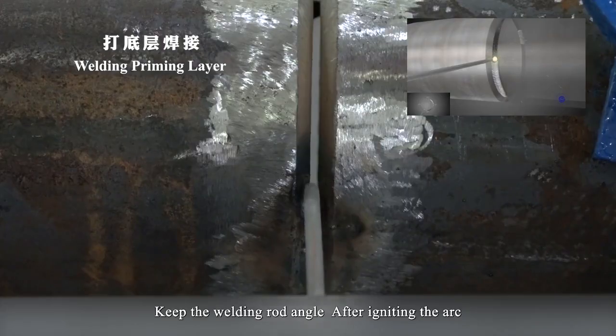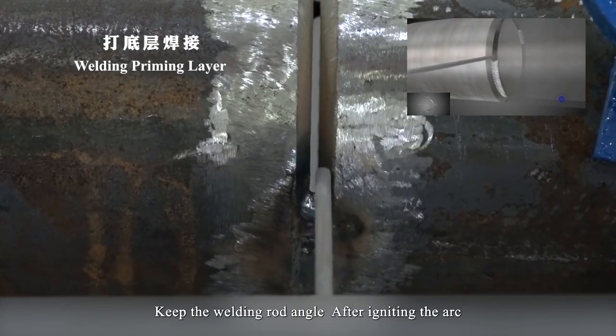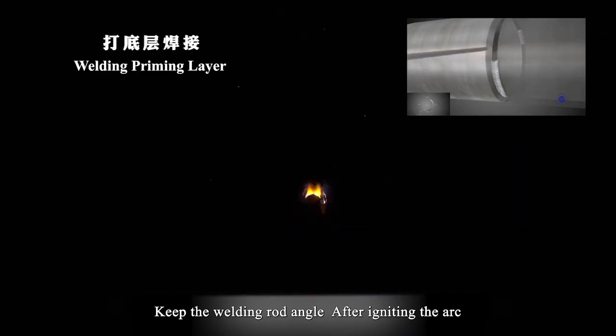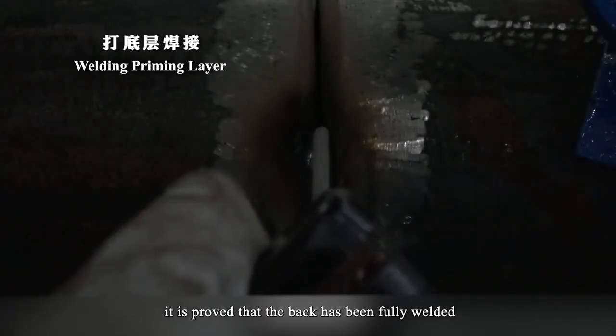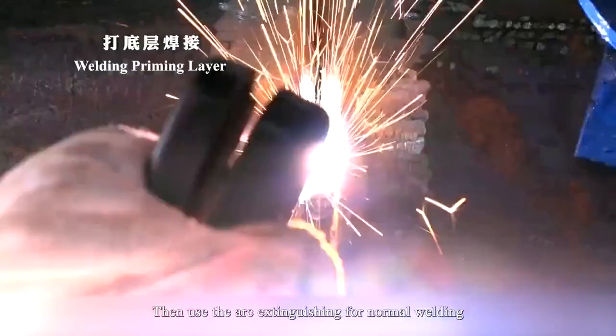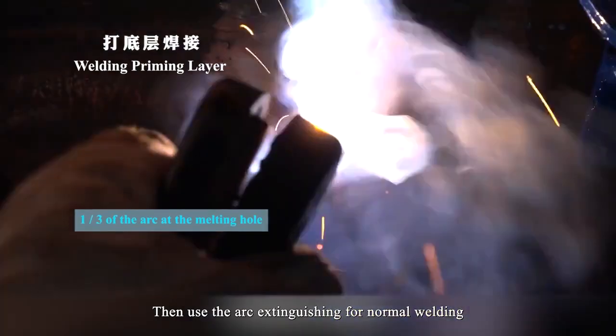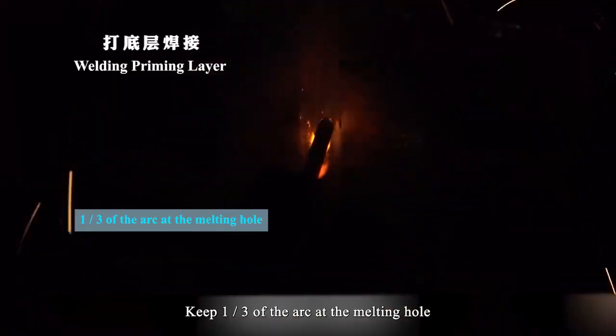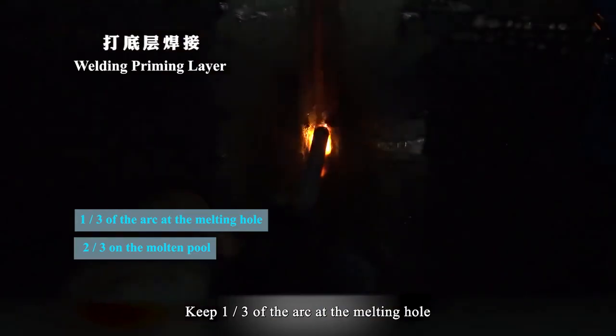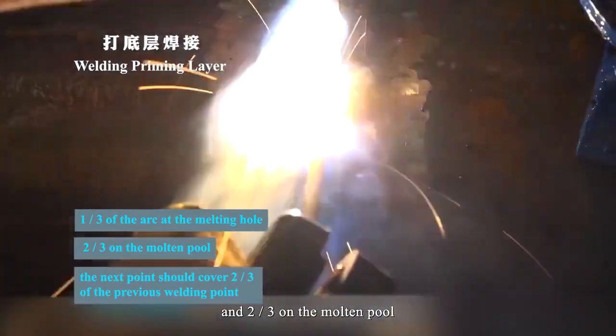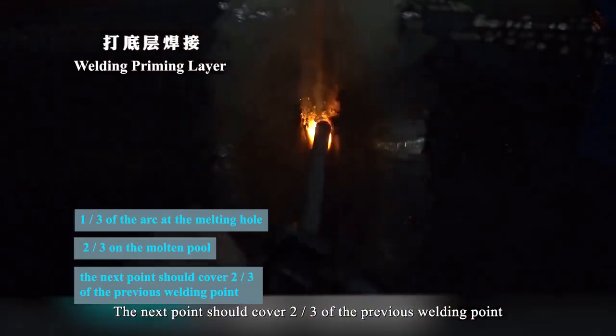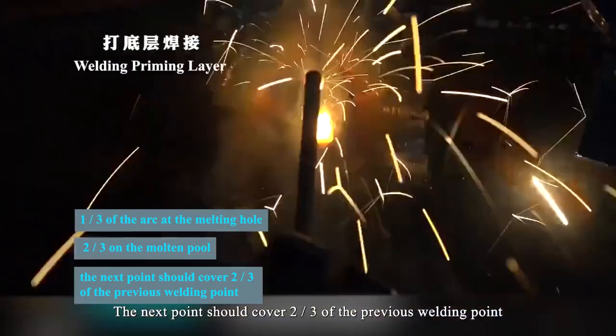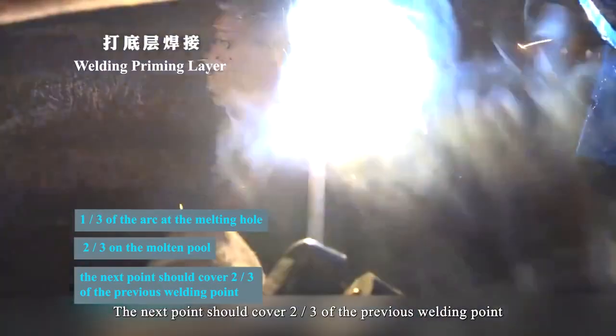Keep the welding rod angle after igniting the arc, quickly lower the arc and stop for a while. After hearing the puffing sound from the back, it proves the back has been fully welded. Then use extinguishing arc method for normal welding. Keep 1/3 of the arc at the melting hole and 2/3 at the molten pool. The next point should cover 2/3 of the previous welding point.